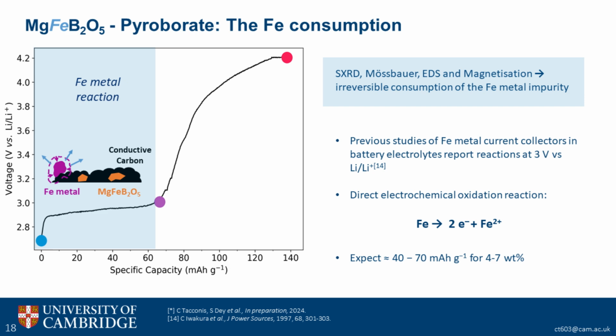And we went in to look at what could be the process leading to this electrochemical capacity. So what we see from powder X-ray diffraction, some Mossbauer, the EDS, and some additional magnetization, is that we've got an irreversible consumption of the iron metal impurity. There are some previous studies of iron metal current collectors in battery electrolytes. And what they show is that around 3 volts versus lithium, you start seeing these really strong corrosion currents. And so what we propose is a direct electrochemical oxidation reaction of the iron metal in our sample through a 2-electron process. And when we did some math to figure out what capacity we'd expect based on the weight percentage of iron that we have in our cathode, we see that we'd get about 40 to 70 milliampere hour per gram, depending on the specific synthesis. And that matches really well with this plateau that you see below 3 volts.